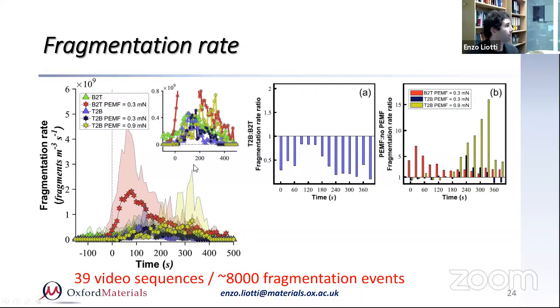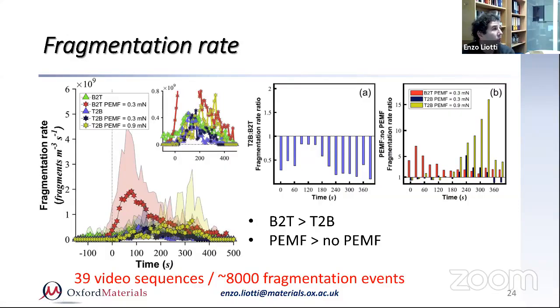If we compare the top to bottom with the bottom to top, this graph here, the A, shows you the ratio of the fragmentation rate of all the top to bottom compared to the bottom to top. We see that essentially solidifying the material with the growth from the bottom to top was always favored. The fragmentation rate was higher at any time during the experiment. While equally, every time we use a magnetic field, we obtain more fragmentation than without it. So the bottom to top is always higher than the top to bottom, and so it was when the electromagnetic steering was present compared to the case without.